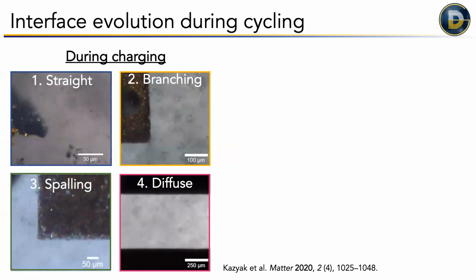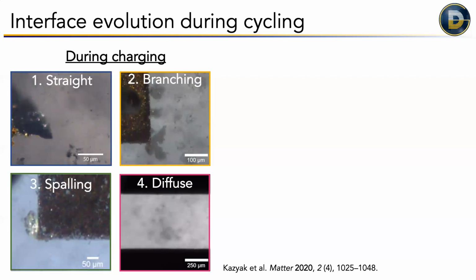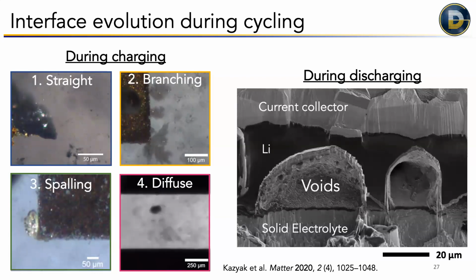Almost done. So there are other challenges. It turns out that solid electrolytes don't just inherently solve the dendrite problem. You can still get these lithium growths that penetrate into solid electrolytes because there are defects and things. And this is where making 10 or 100 million becomes hard, because if one in every 10,000 has a defect, you might get a short circuit. Now, because it's a solid state battery, it's not going to catch on fire, but it will kill the battery, so it's not good. And then also during fast discharge, you might not strip the lithium uniformly, so you can get these voids, which cause issues as well.